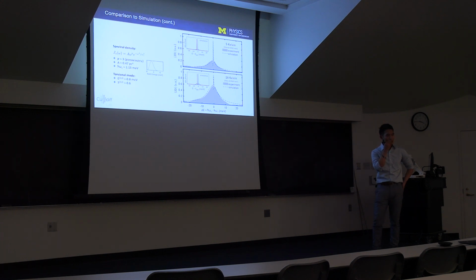I never thought about it in those terms. But when the single dot luminescence showed multiple phonon sidebands, you could see 1, 2, and 3 phonons being involved. Those were optical phonons. Those are not continuum. I think the answer is that there are multiple. The harder you drive the vibrational coordinate, the more replicas you get. Plus you have a continuum of phonon energies because they're acoustic phonons, so everything just gets smeared out.